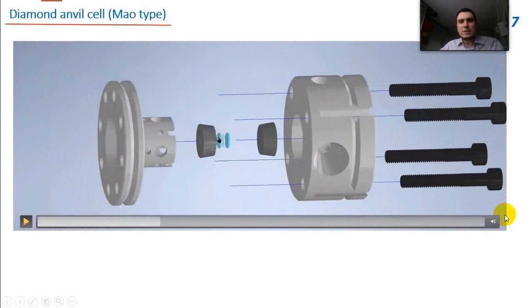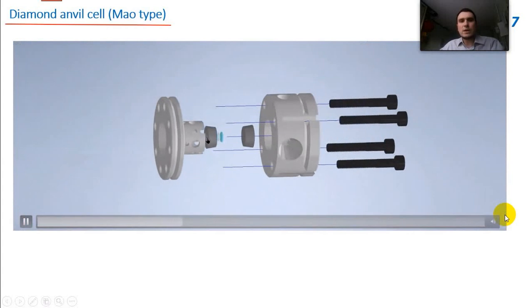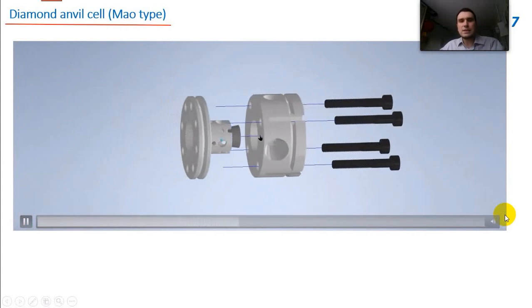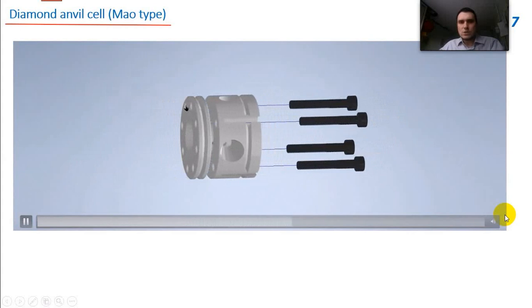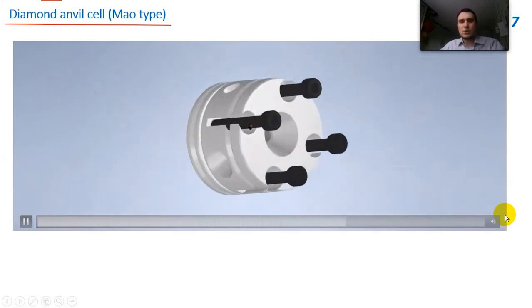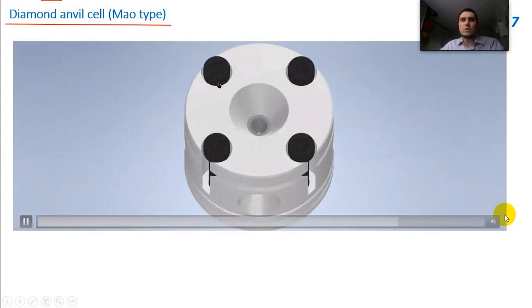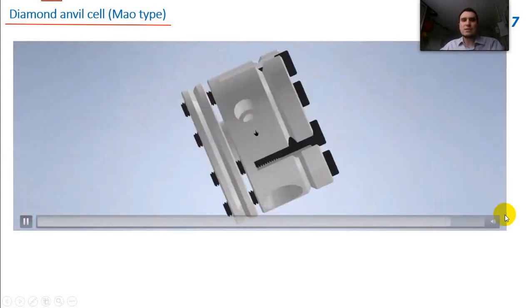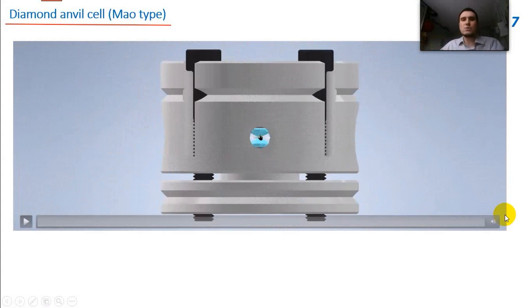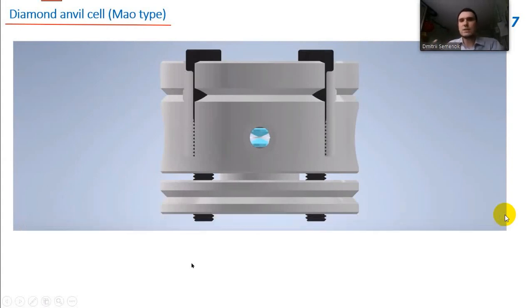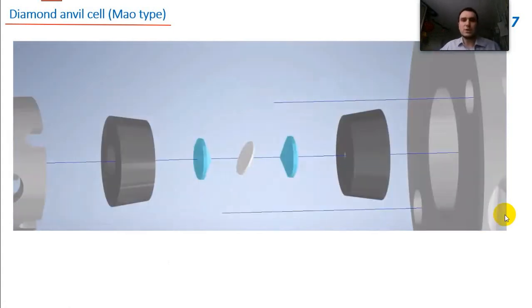We need to glue these diamonds to the seats. It's a special plate made of tungsten carbide, and this plate is also glued to the piston and the cylinder which form the diamond anvil cell. We can tighten this cell using the screws, and when we increase the pressure on the piston, the pressure transfers to the seats, then to the diamond, and then to the sample. That's how we create high pressure in our sample, synthesize something, and investigate the behavior of matter under pressure.